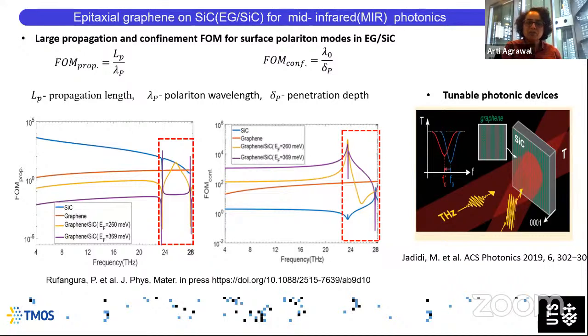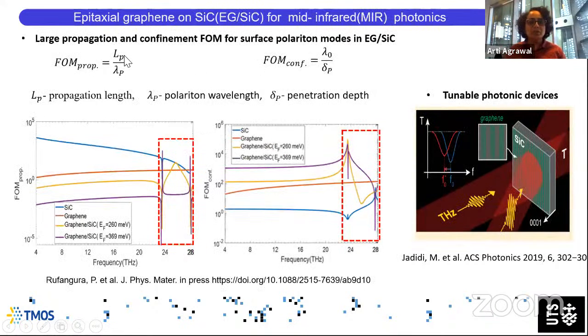The first figure of merit is to do with propagation, which you see on the left top here. This figure of merit is the polariton propagation length divided by the polariton wavelength. This tells you how much it will propagate before it dies out. And as you can see in this graph, the blue curve is for the silicon carbide, the red is for graphene, and then the orange and the purple are for graphene on silicon carbide for different Fermi energy of graphene. This is perhaps not so interesting because you can see within the Reststrahlen band how the materials behave.